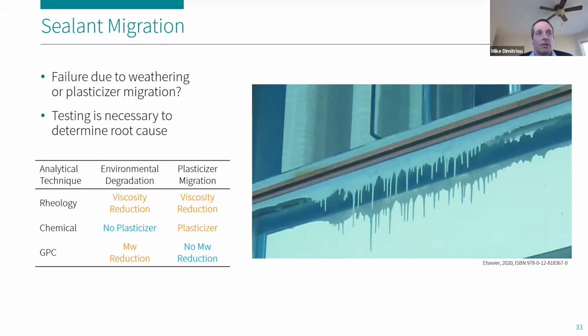without any additional testing and only this visual observation, a scientist may see this and say that this could be a result of environmental degradation, but it could also be a result of plasticizer migration. Like I said earlier, plasticizer migration can reduce viscosity and it can increase the flowability of materials. And I think it's clear to say from this image that this material that is starting to drip down a glass pane is in fact showing more flowability than you might expect.